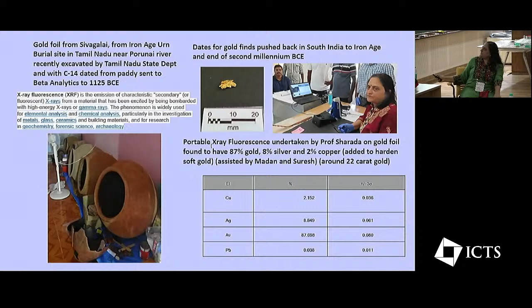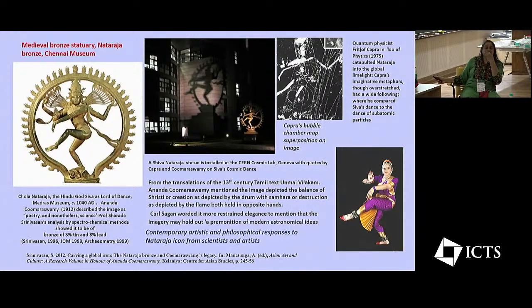And you see here, it's very high purity gold, about 87%. And there's some silver also, 8% or so, more in the range of electrum in a way. But it's interesting that we now have these techniques to do the analysis.